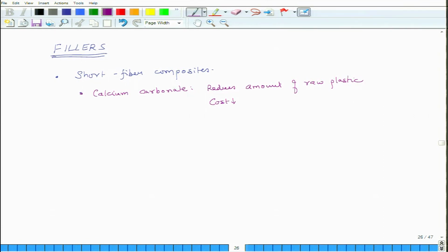Besides that, it also does something good. It controls shrinkage, because if you remember, a lot of these plastics after curing, they shrink. So, it reduces shrinkage. Surface smoothness, because in a lot of these day to day products you need a good surface finish for aesthetic reasons, and it eliminates sink marks. So, what is a sink mark? It is a mark when you do injection molding, there are places where you get sink marks, and that comes out as a cosmetic defect. So, it eliminates those sink marks or at least reduces them.